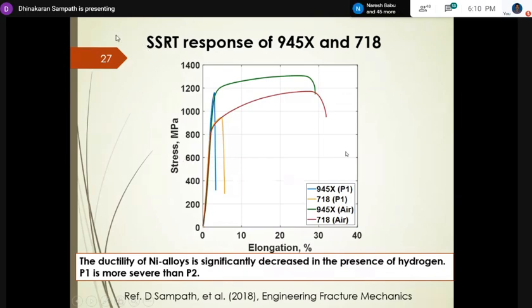And now the slow strain rate test (SSRT) response of 945X and 718. As I said, the peak-aged material will have high strength. So 945X has high strength compared to 718, which is the red curve. For 945X, in the presence of hydrogen, it fractured very close to the yield point. In the case of 718, which has slightly higher ductility and higher elongation, in the presence of hydrogen it showed higher ductility compared to 945X. So this is what we get from the slow strain rate test.